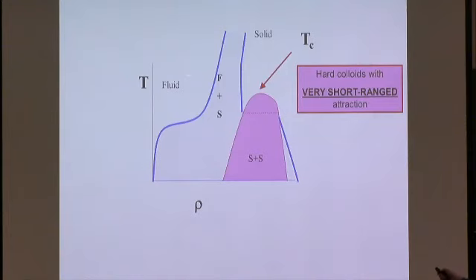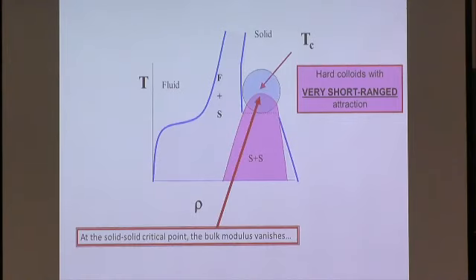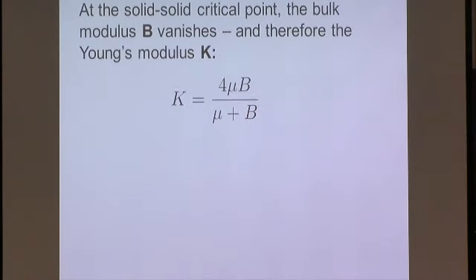I'll be talking about the situation where this is a two-dimensional or a quasi-two-dimensional system, and then you have this critical point in the solid. Now, what does that have to do with bond-ordered phases? The important point is that if you have a critical point, density is the important variable, then the compressibility of that crystal becomes infinite, or conversely, the bulk modulus vanishes. Now if the bulk modulus, called B, vanishes, then in terms of the bulk modulus and the shear Lamé coefficient, that's the elastic constant that determines this deformation, you can express the Young's modulus, K, which is another quantity that is particularly important when in a minute we start talking about dislocations. Where the bulk modulus vanishes, the Young's modulus vanishes.